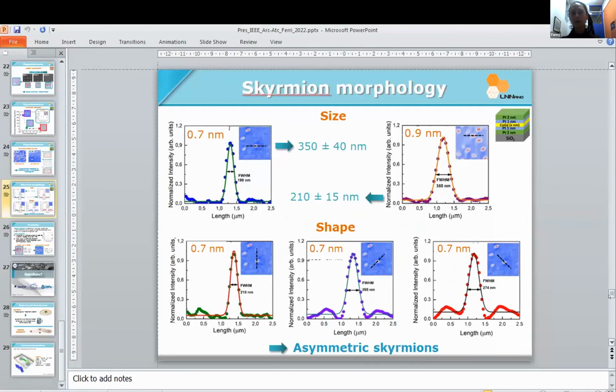We also looked a little at the morphology of these skyrmions. This is a part that is still ongoing. The size of the skyrmions is quite large, and they vary, being larger for a thinner thickness. For 0.7 nanometer, remember that we had a lower density, and we have larger skyrmions. At 0.9 nanometer, we have a higher density and smaller skyrmions, but they are still pretty large, 210 nanometers. Something interesting is that they are not symmetric skyrmions. If we take cross-sections of the same skyrmion at different angles, we can see that they are asymmetric. Of course, when we used lateral confinement in nanodisks, they were symmetric skyrmions.